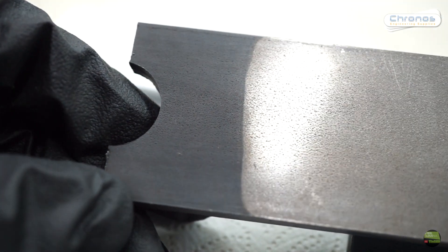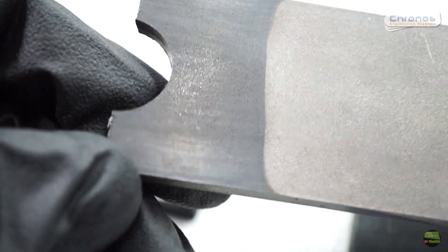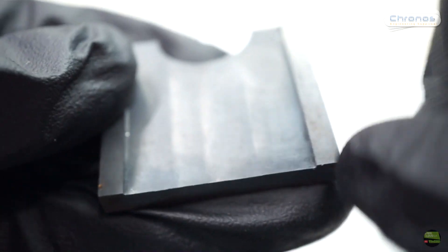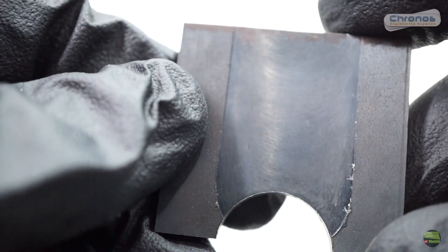And that's the result. On that raw piece of steel is still protective oil. We can see where the part is black and it doesn't shine anymore. The other part is a bit milled, oiled and rusted. On the milled area we got very nice evenly blacked surface. On the oiled parts from the side it's a bit more shiny and the black isn't that deep. And the rust is still there, just a bit less visible.